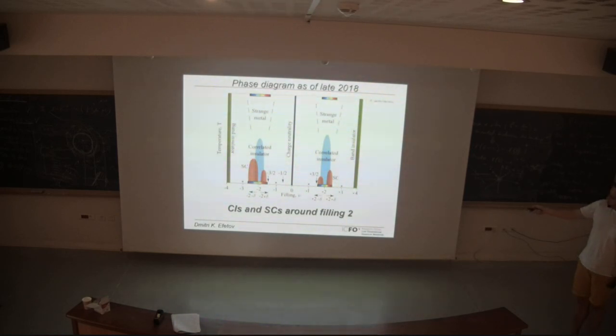And then flanking these correlated insulating states, left and right of them, superconducting states were observed. So if we start from a correlated insulating state and dope it slightly on the electron or the hole side, in both cases you end up with a superconductor. And of course, this raised a lot of questions whether these superconductors actually inherit the phase of the correlated insulator, or maybe it is similar to the cuprates. One possibility is that the correlations in the insulating state actually give rise to the superconducting behavior of these superconductors. Okay, so this was